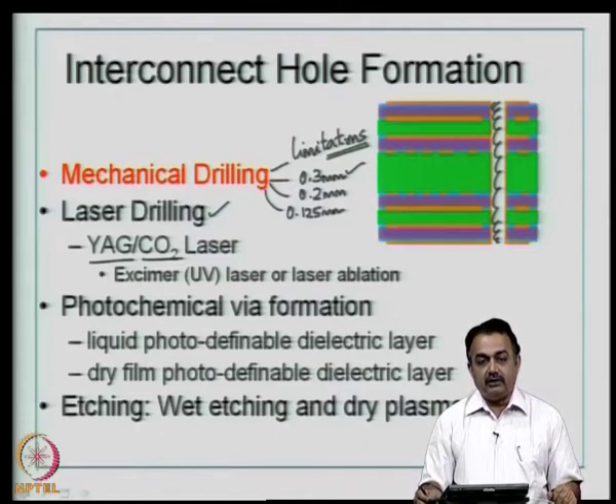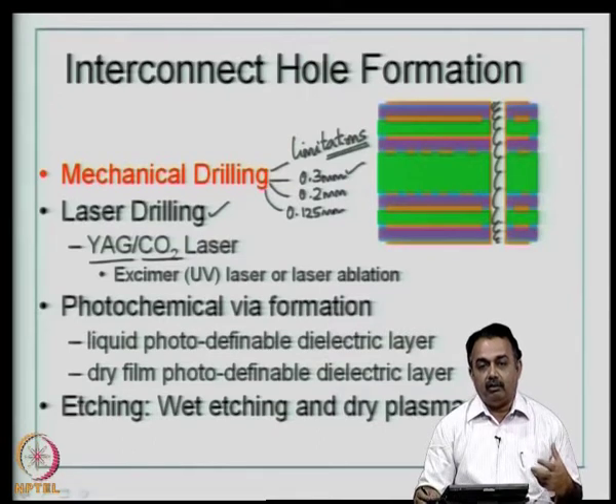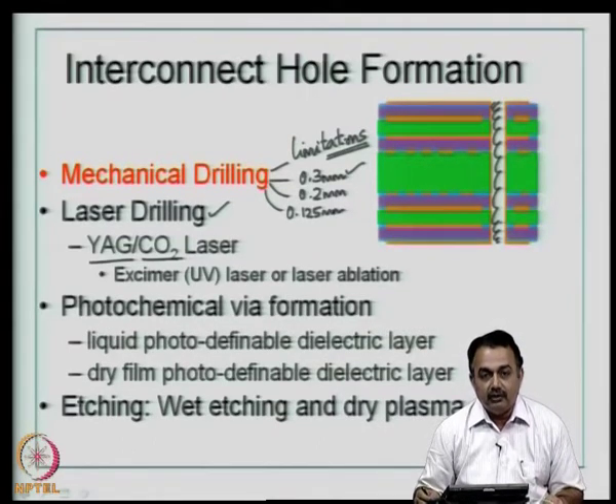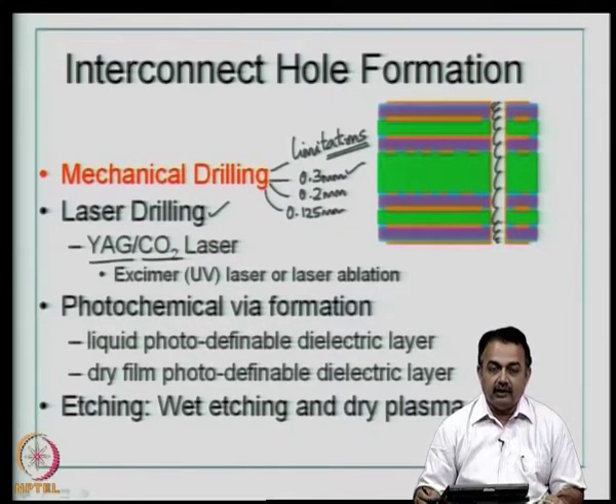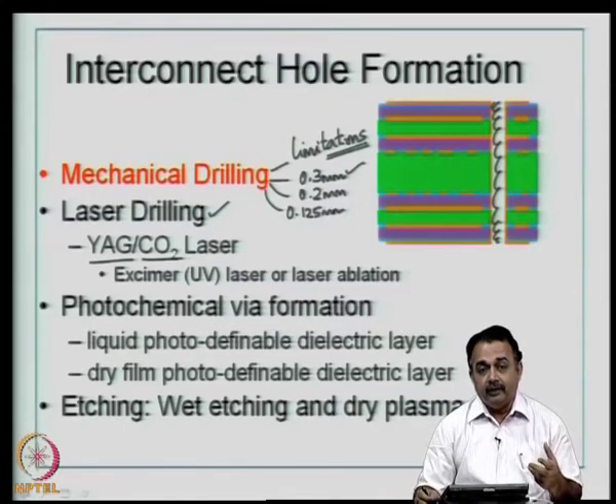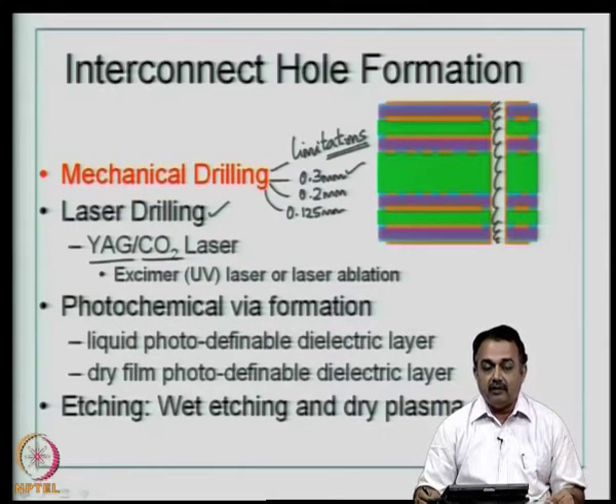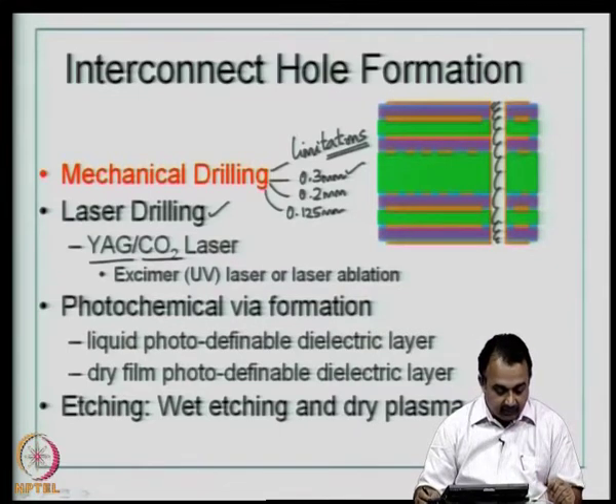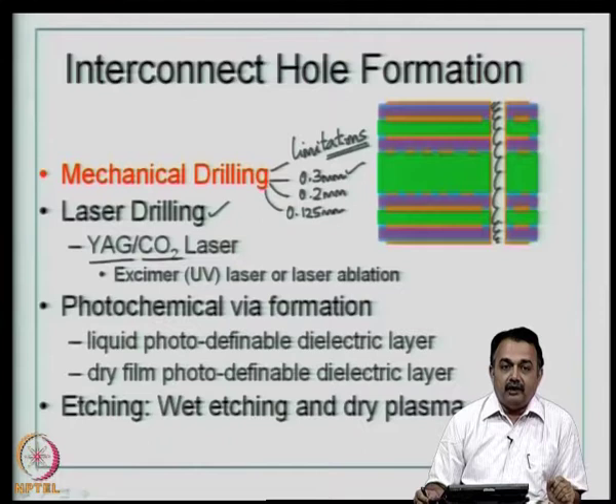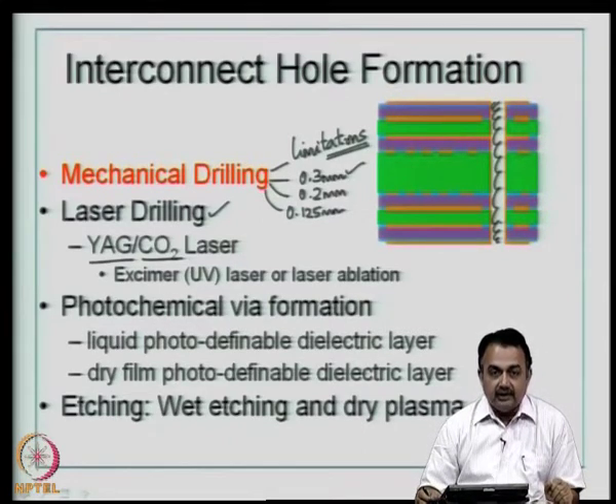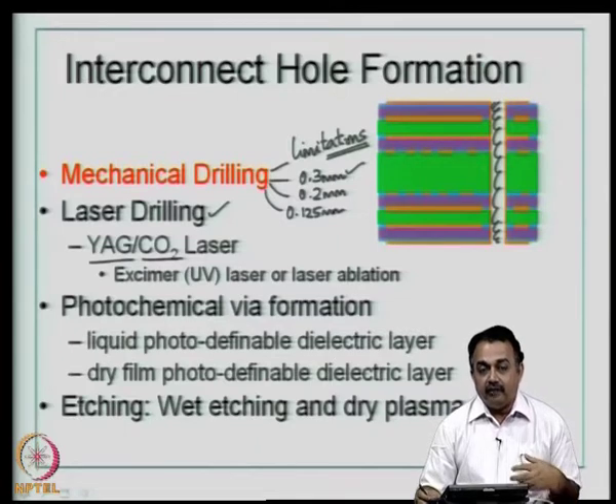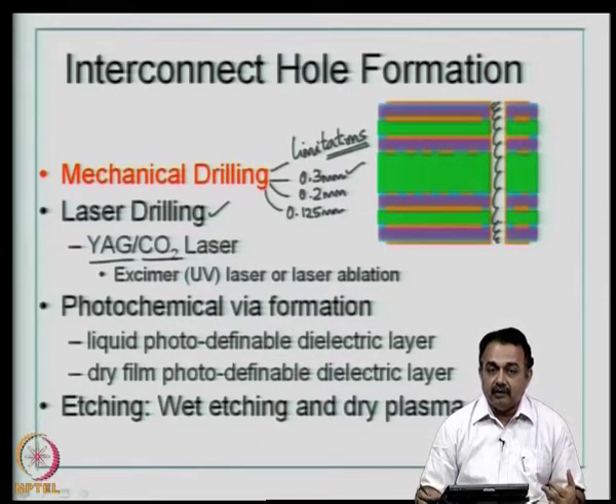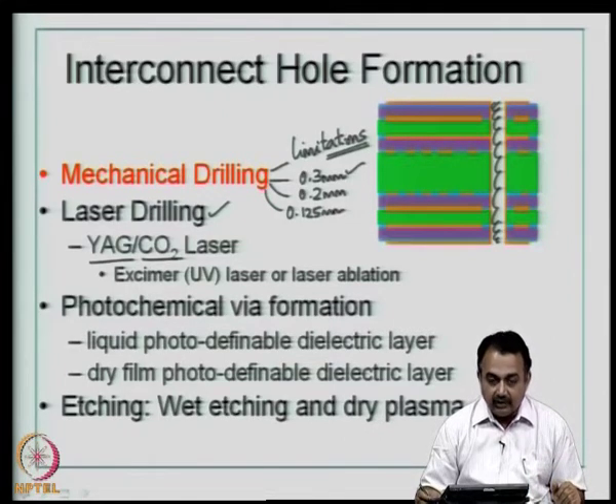Now, the process looks simple in description, but again we are talking about the quality of the hole that is required if you are going to use laser drilling for a through hole with a moderate aspect ratio, and then follows the adaptability or the conditions of the hole wall for subsequent electrolysis plating. Because if you drill a hole wall which has got a lot of debris and defects, then it is going to be reflected in your electrolysis copper plating. Therefore, one has to be careful about what kind of methodology you are going to use. But laser drilling equipments are becoming very common, they are affordable, and they have indicated that you are going to get a very high throughput and yield in terms of number of PCBs produced using these laser drilling machines.